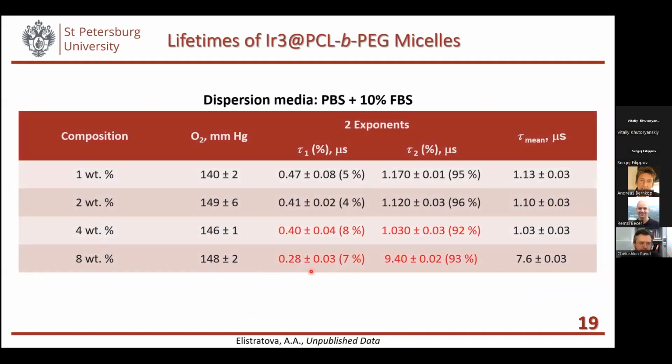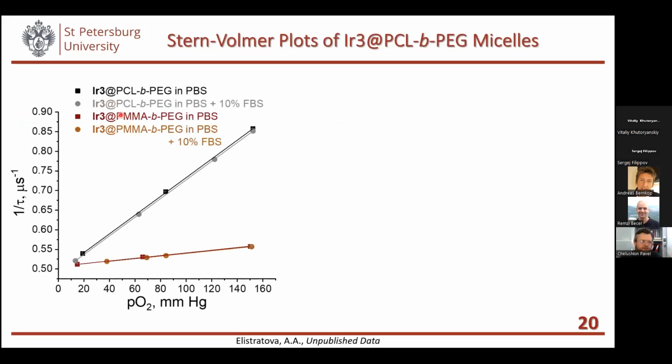We have found that high payloads are not good, and low loading is more beneficial, and we managed to use in further experiments 2 weight percent nanoparticles. And we, of course, took polymethyl methacrylate as a control in these systems and have performed calibration.